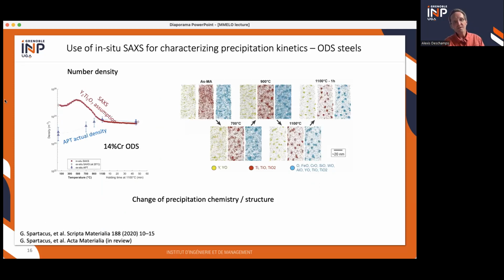Then from small angle scattering, you can get the number density if you make a hypothesis on the nanoprecipitate composition. So here, if you suppose it's a pyrochlore phase, then you can get the number density. And you can compare this number density with atom probe tips. Of course, they are not in situ. You can't do in situ at 1100 degrees Celsius in an atom probe. And you can compare these number densities.